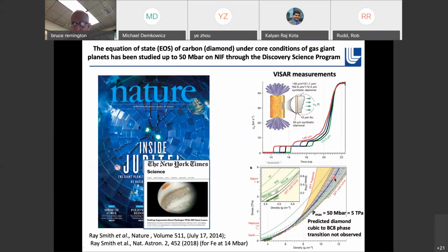It was smooth all the way through. So that gave us the first hint that the kinetics of the phase transitions is happening on timescales that are not so different from the experimental timescale. So exactly how long it takes to go through a phase transition can now be probed in these high pressure experiments, as well as getting the compressibility.